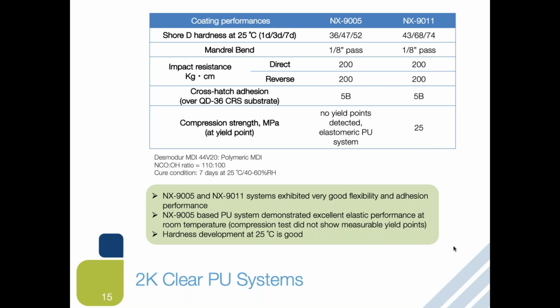So from this study, what we have seen is that 9005 and 9011 can offer fast cure. As you can see, it shows the hardness development at day 1 and day 7. It's pretty fast. And then it can also achieve excellent flexibility and impact resistance. In the mandrel bend study, it passed, and then impact resistance was 200. And also you can have excellent adhesion on, in this case, a metal substrate.